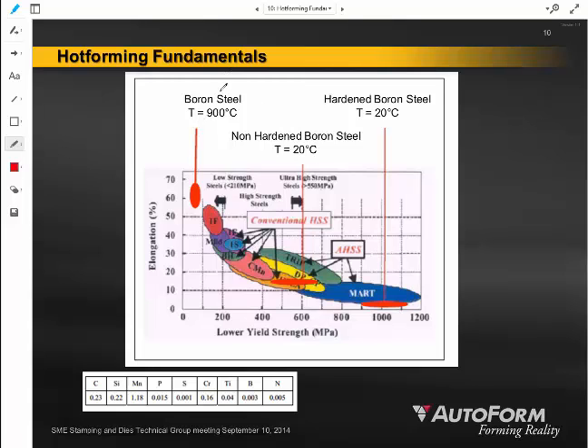When we talk about hot forming and hot stamping these materials, we're usually talking about one very specific type of material that you might call boron steel. And I've also seen that steel called out with a numerical designation. Let me make sure I get this right. 22MnB5. That would be this boron steel material whose chemical composition I have in this little table at the bottom of this slide. Right? So boron steel is a high carbon steel. It's got a significant amount more carbon than would a typical stamping steel. When we think about mild steel and a draw quality, we're usually talking about material that has a carbon by weight percentage at 0.08 or below.